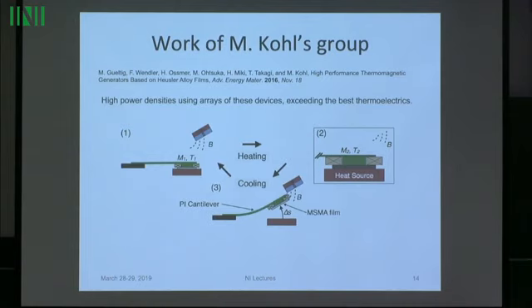So what's a good shape for making the big dm dt give you a big dB dt? It's a long, thin shape, it turns out. So a pancake is a very bad shape. If you wrapped a coil around a pancake, you'd get hardly any induction in the coil. But a very long shape is a good shape, okay? So this phase-changing ferromagnetic material should be in the shape of a rod.